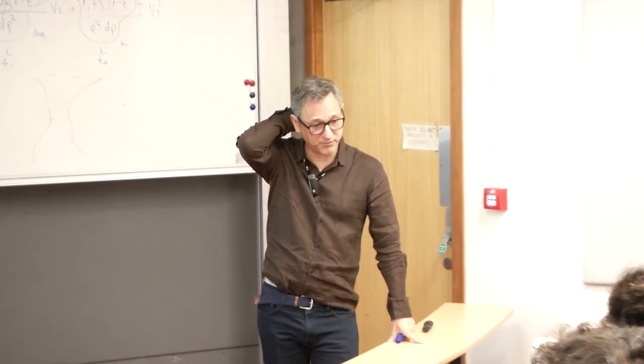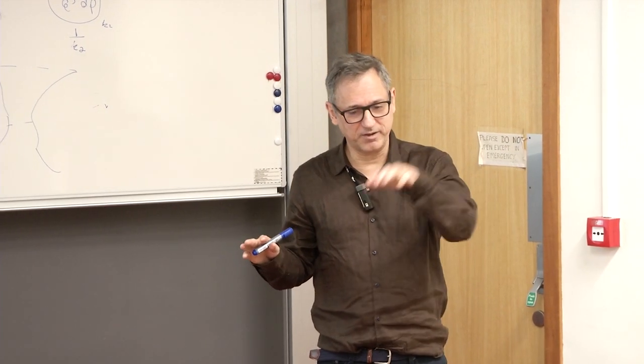So from a material perspective, my first question is, there are defects in the material which are quite inevitable. Is it possible to measure these defects? Is it possible to quantify if the defect will cause any extra flow? For example, we measure the permeability for corrugated fiber boards, fiber sheets, fiber cement sheets. And you have micro cracks along the corrugation. So when you measure, we can detect that. We have a perfect fiber sheet and measure permeability. Then I will show you one.